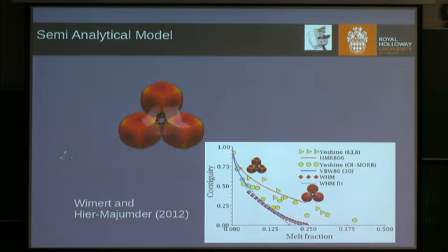We're just showing 3 grains, and you can see the tube is kind of shown here. The tube area is increasing as the melt fraction goes from about 5 volume percent to about 25 volume percent. The color code is the degree of flatness. You can take that as an approximation for the area of grain-grain contact. So if I were to binarily digitize, those would be the evolution of the contiguity.